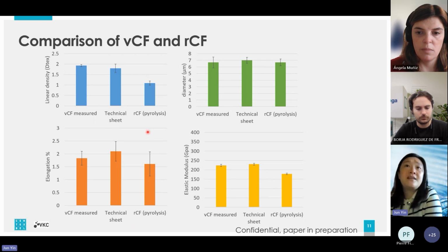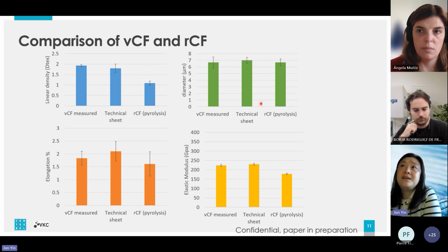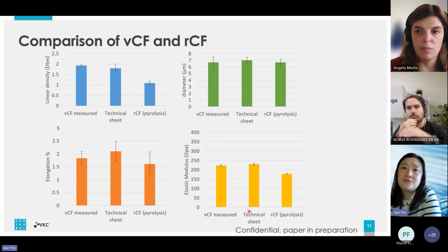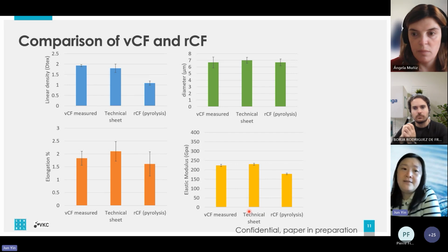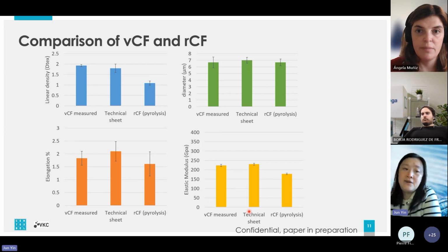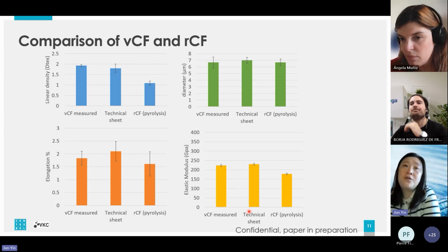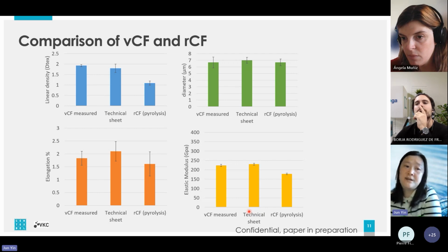Then we measure again on this recycled carbon fiber, the same original fiber after pyrolysis. We can see the linear density decreases, the diameter is almost the same, and the mechanical properties, elongation and elastic modulus, decrease. So in the future, we will use the same recycled carbon fiber for our sizing development because we can compare it with the virgin fiber.